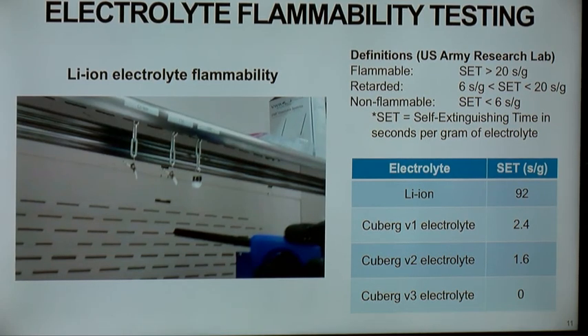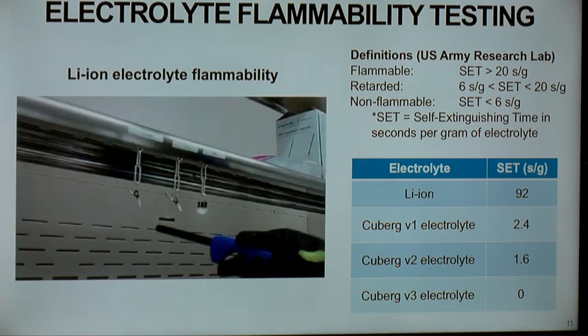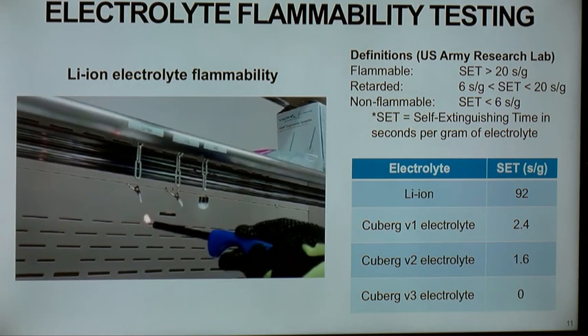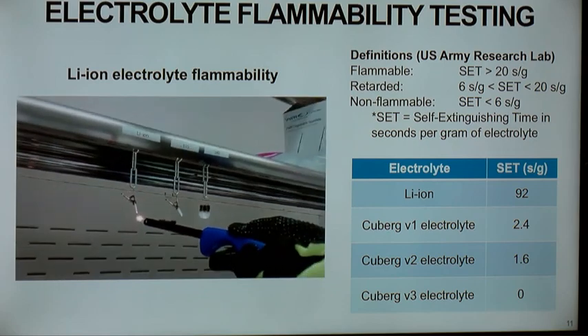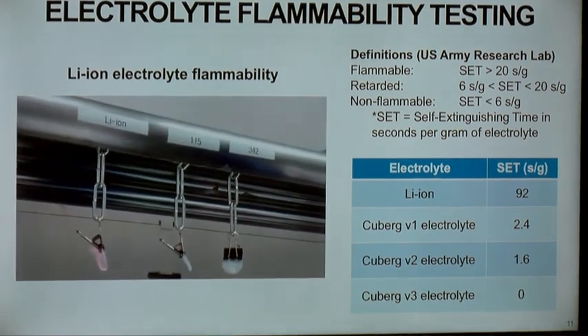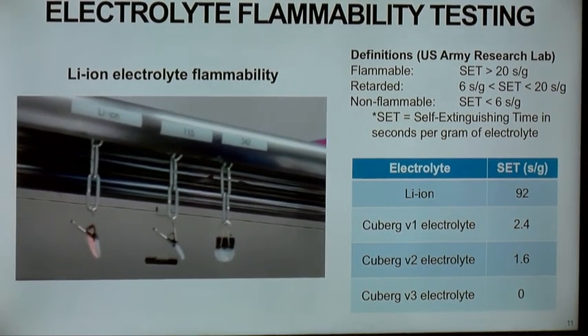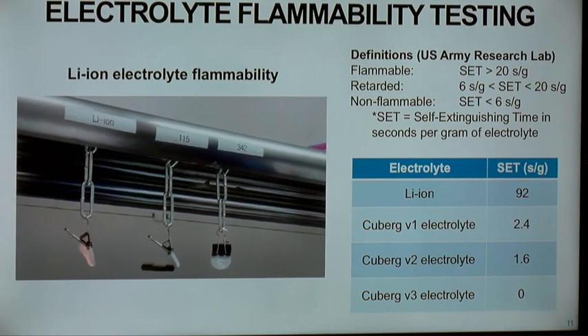And so you take a separator, soak it with a known amount of electrolyte, and then try to light it on fire and see what happens. If you look at this video here, this is us lighting a lithium-ion electrolyte on fire. It's extremely flammable, it burns for quite a long time, and if you calculate the amount of time per gram of electrolyte, you get the self-extinguishing time.